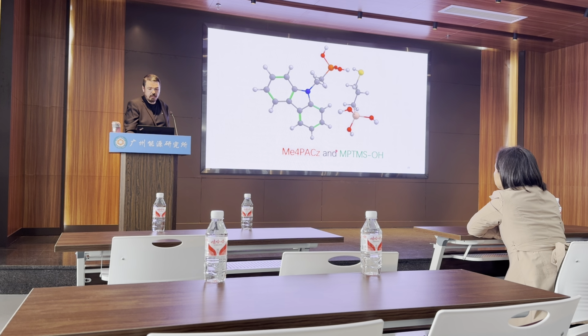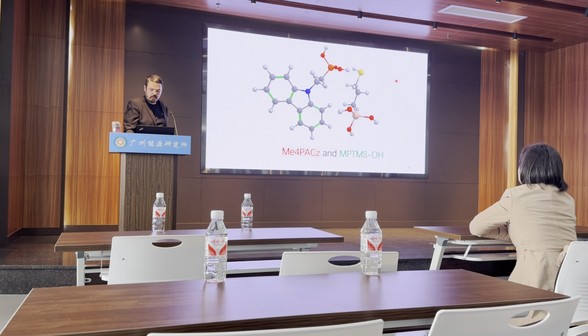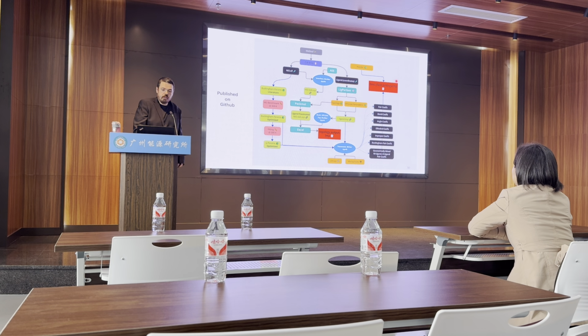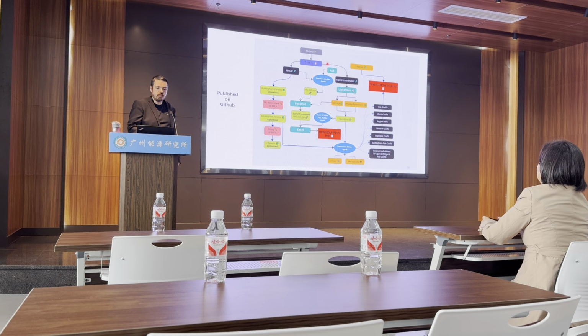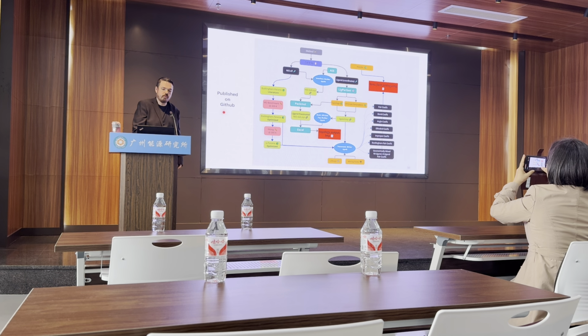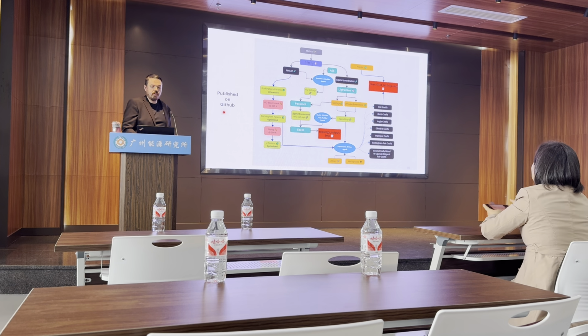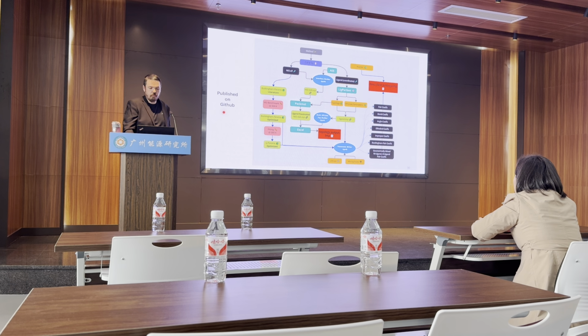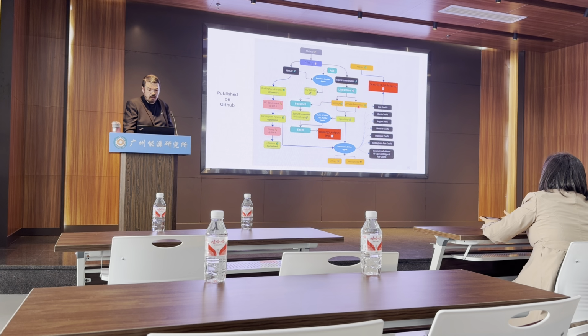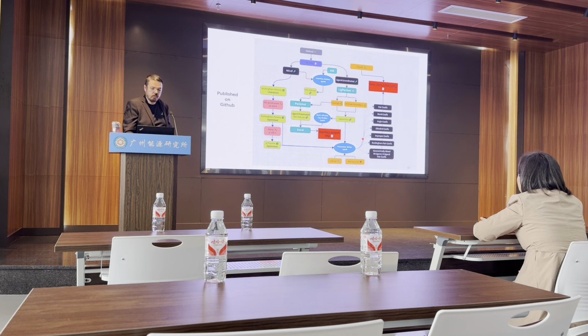So we take Me4PACz and MPTMS-OH with the hydrolyzed tails. A lot of work had to be done to launch this in LAMMPS. LAMMPS is not very easy to work with, so we had to go through a whole process and wrote the code, and we put it on GitHub so other people can reproduce it for other materials. But basically, the whole idea here is we need to train a bunch of force field coefficients, both for the passivators and the nickel oxide. We also had to modify to be compatible with these. So there's also a compatibility problem.